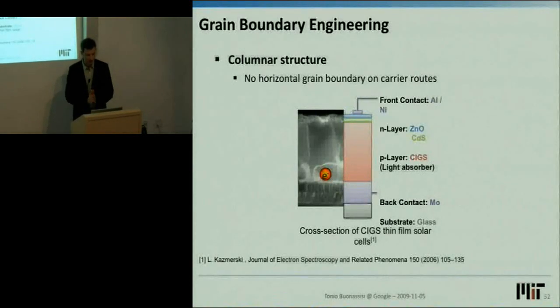So our first step is grain boundary engineering. We want to make sure that these materials have large enough grains such that the grain boundaries do not inhibit carrier transport. And let me just show you here the grain boundaries highlighted in a cross-sectional scanning electron microscope image of a thin film material. If this is our little electron at the bottom, it has to be able to make its way out of the material without interacting with the grain boundaries.